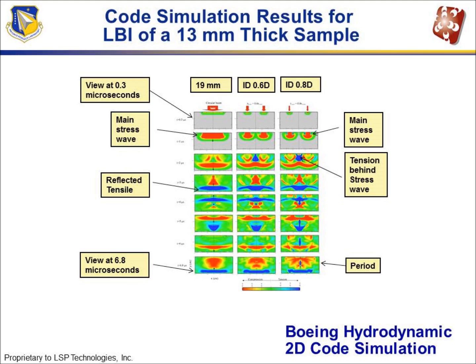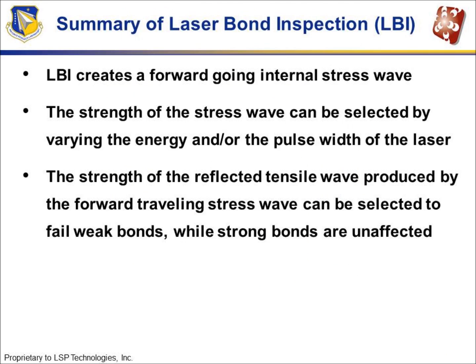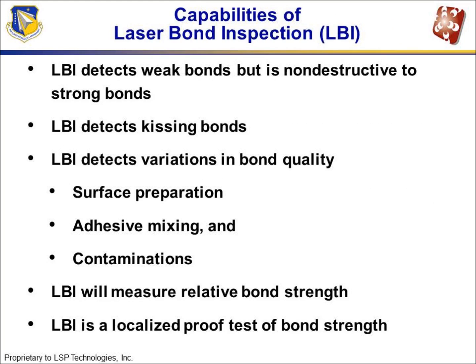It can also detect kissing bonds. These are bonds in which the bond line is in intimate contact with the laminate that is around it. There's no gap between the bond line and the composite material, but it doesn't have good adhesion to the surface. So there's a weakness there that would be important to detect. LBI will also detect variations in bond quality, different types of surface preparation, adhesive mixing, and if there's contamination in the bond line material. It is a localized test of bond strength in that it's measuring the strength of the bond that is in the region of the diameter of the laser beam being used to interrogate the bonded structure.